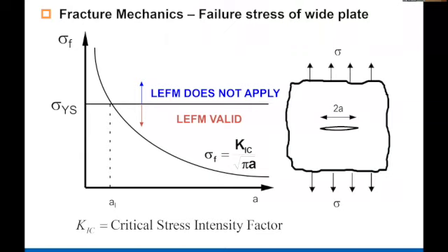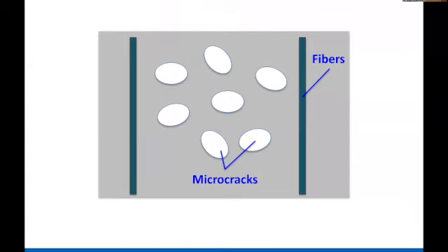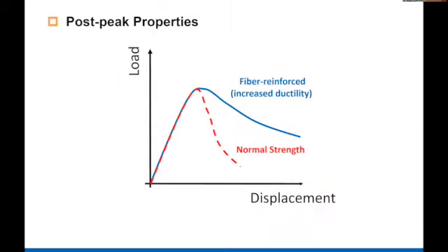And it turns out that at that scale, before fibers can see a crack, there are lots of micro cracks. So fibers will not be effective until the macro crack forms or the peak stress is reached.